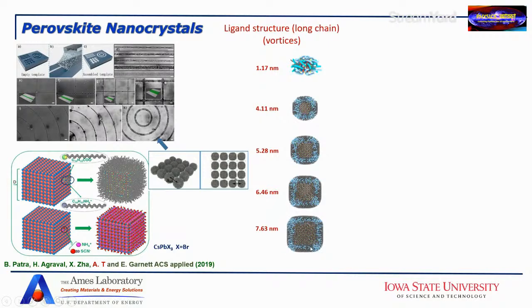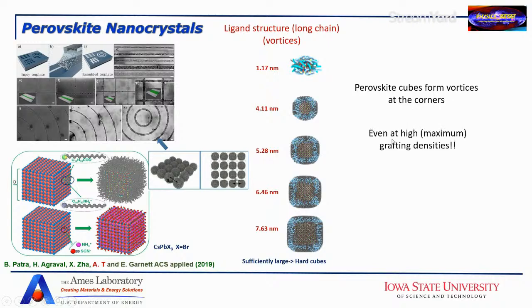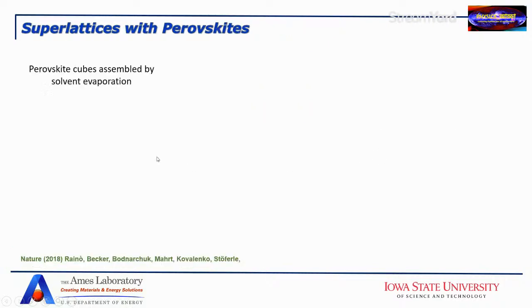And they become floppy around the corners, as we see here. So this is what we have. If you have sufficiently large cubes, they become like hard cubes, except at the corners. So perovskite cubes form vortices at the corners, even at high density.